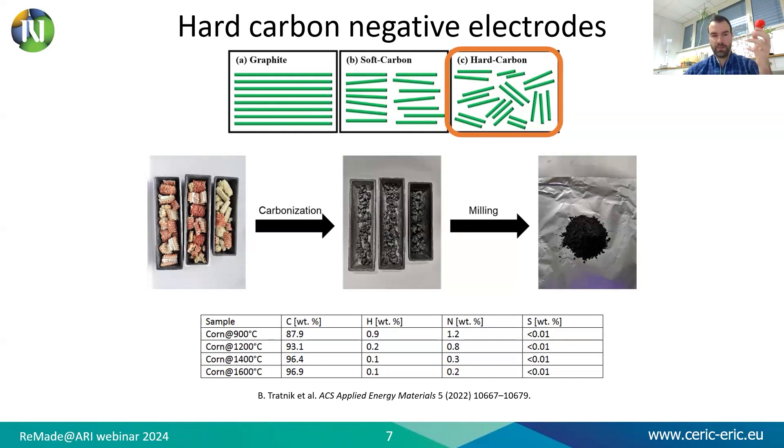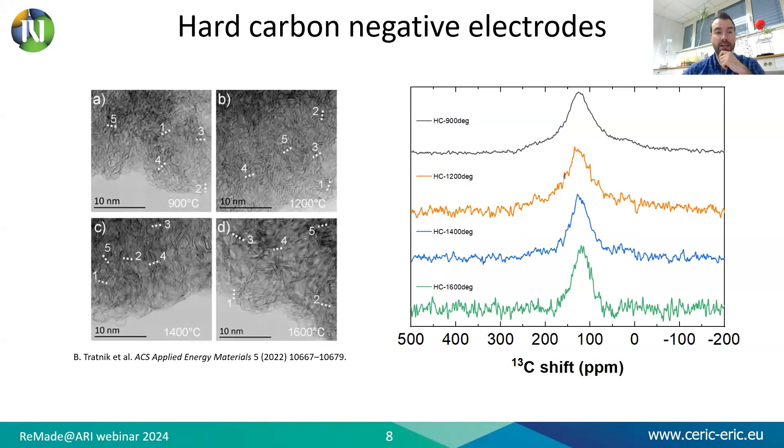In this study, we show physical and electrochemical properties of this half-cell corn-cob-derived hard carbon, established with ex situ and operando solid-state nuclear magnetic resonance. The gradual ordering of hard carbon is well illustrated by scanning transmission electron microscopy, showing a gradual increase of graphene lines at higher carbonization temperature. On the right is a solid-state NMR measurement of the same electrode powder at different carbonization temperatures, and a mild narrowing of the signal due to ordering at higher carbonization temperature is also detected with NMR.